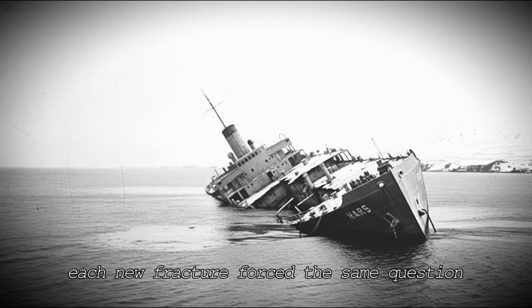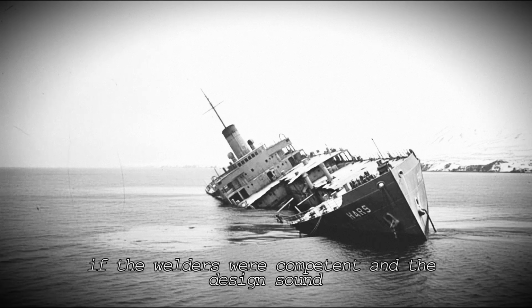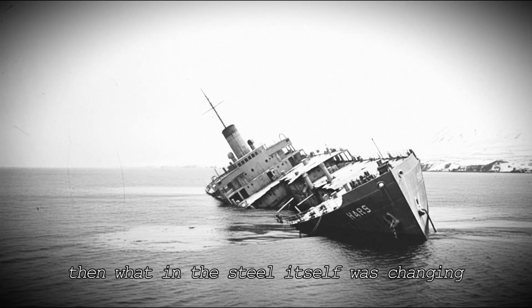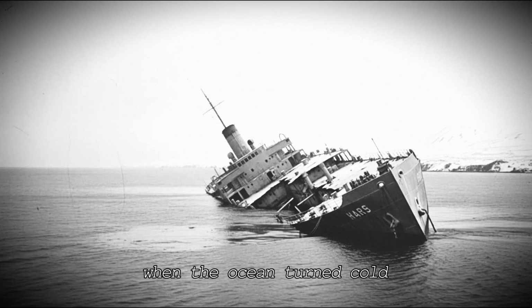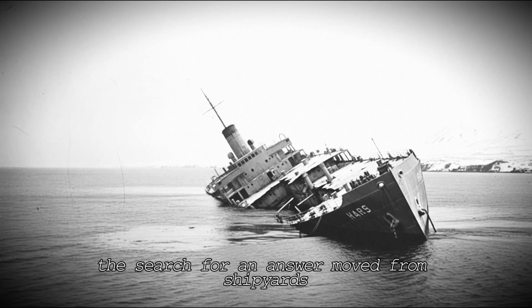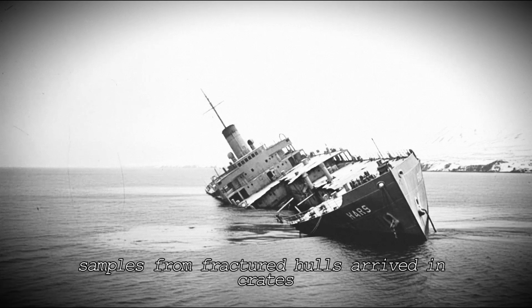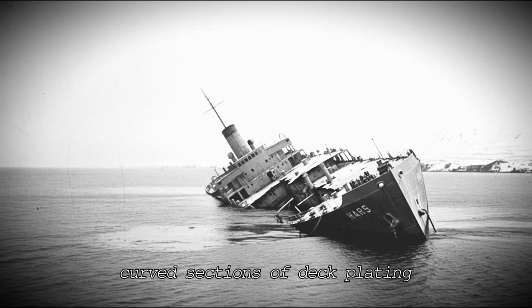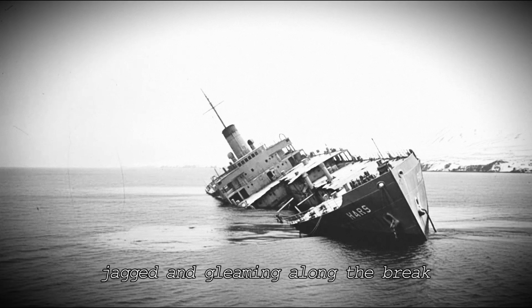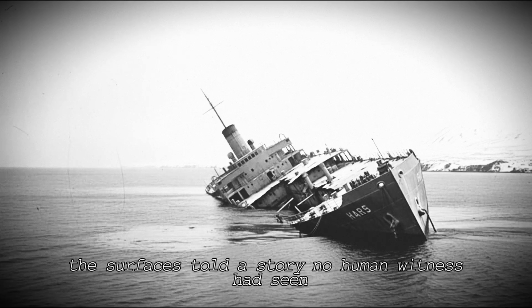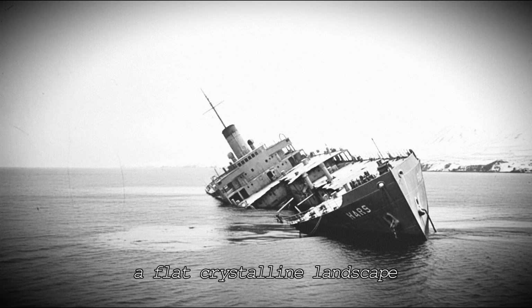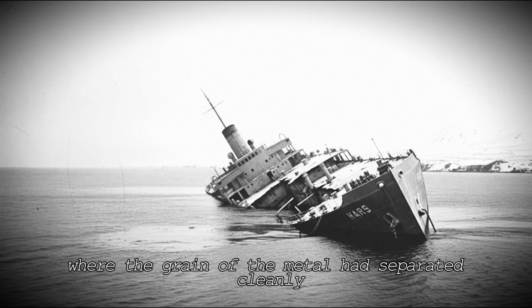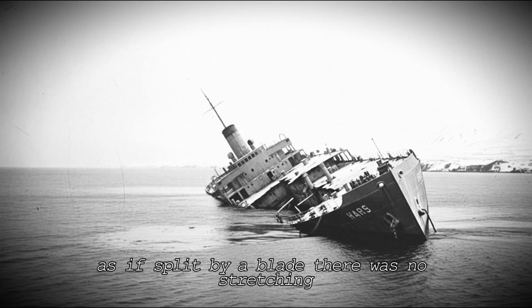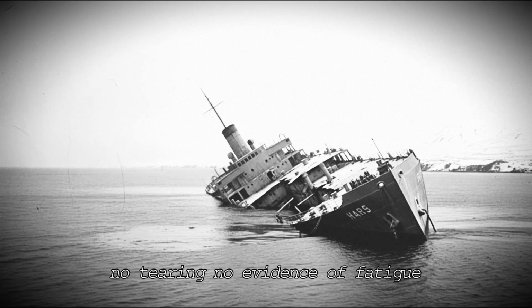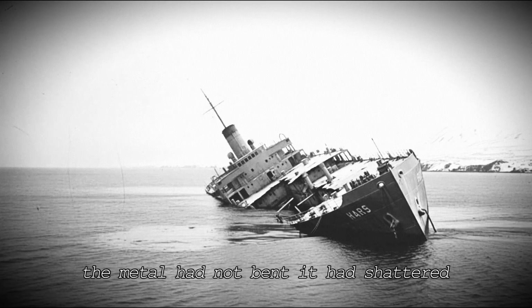Each new fracture forced the same question. If the welders were competent and the design sound, then what in the steel itself was changing when the ocean turned cold? The search for an answer moved from shipyards to laboratories. Samples from fractured hulls arrived in crates, curved sections of deck plating, jagged and gleaming along the break. Under magnification, the surfaces told a story no human witness had seen. A flat, crystalline landscape where the grain of the metal had separated cleanly as if split by a blade. There was no stretching, no tearing, no evidence of fatigue. The metal had not bent.